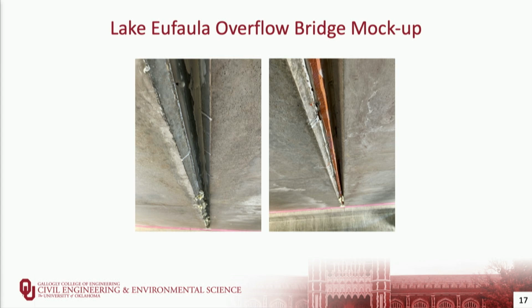Here you can see the bottom of those joints on the bridge mock-up after casting. You'll notice that there is some spray foam insulation along that joint, which is where they had some leaks in the initial casting. UHPC is, again, very flowable. It will find any opening in the formwork that's there, and so the formwork needs to be watertight to keep that material in. Fortunately, those things happened on the mock-up, not in the actual bridge.